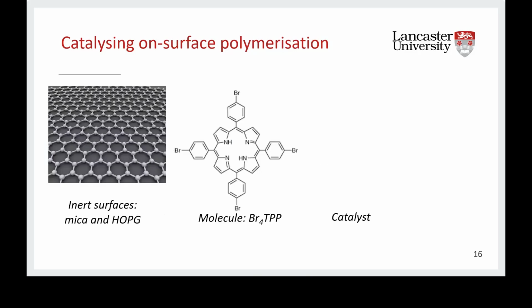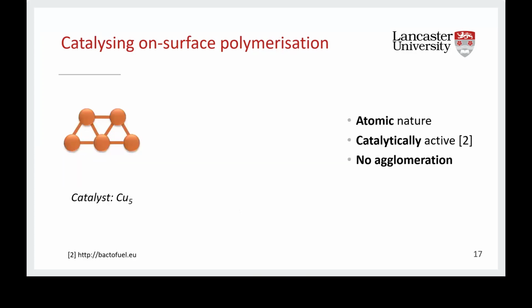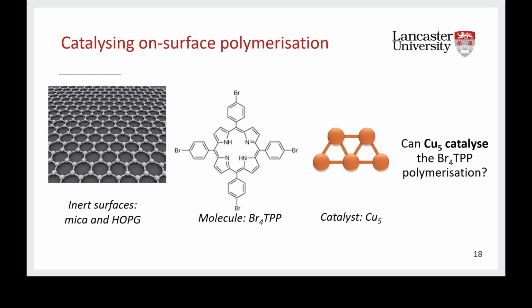And finally, we have the last character, the catalyst. We have a very special one called the Cu5. Cu5 are clusters made of just 5 copper atoms. And for this reason, they exhibit an atomic nature, so discrete energy levels. But they also are catalytically extremely active because the coordination number of each copper atom is very low. And they actually have been used for the hydrogen evolution reaction, for example. But the interesting property is that the Cu5 do not agglomerate together, so they always remain Cu5 and can thus be used for the polymerization.